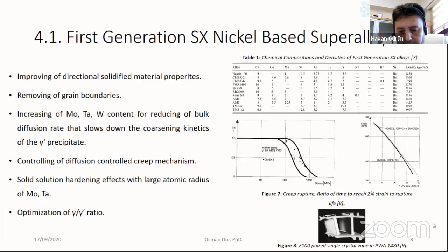These molybdenum and tantalum additions increase the solid solution hardening effect with large atomic radius. Controlling of this diffusion controlled mechanism was successfully done. Optimization of the gamma prime, gamma ratio was again successfully completed in this generation. As you see in the picture, these are the elemental analysis and densities of the single crystal. In the other picture, PWA 1480 vane pairs are shown, which were used in the F100 engine.